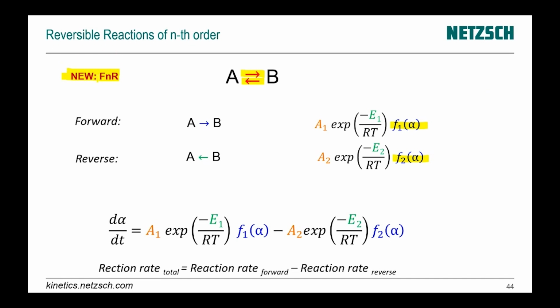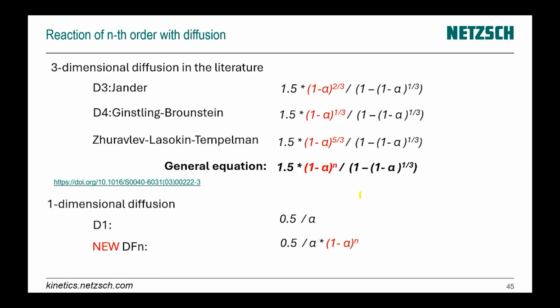Then you can use a reaction FnR. Then the next reaction type, a new reaction type, is reaction of nth order with diffusion. For 3-dimensional diffusion, up to now it works very well, therefore it is not necessary to change anything. We can just look at the equations. They are always the same, the only difference is in the part which looks like nth order reaction, where we have 1 minus alpha to the power n, and n is the order of reaction.